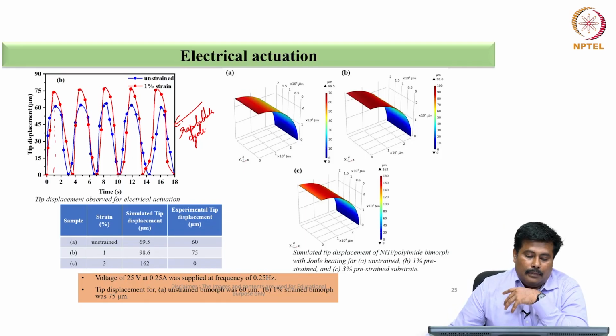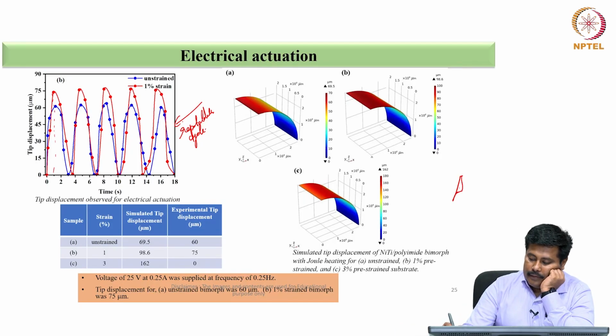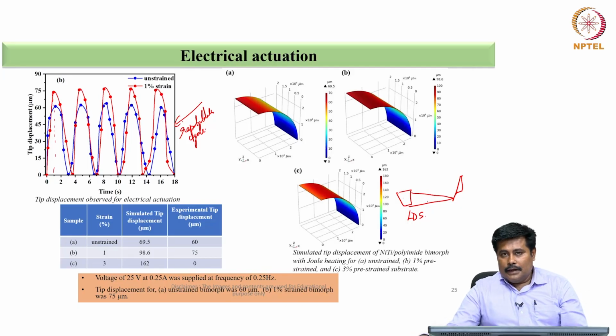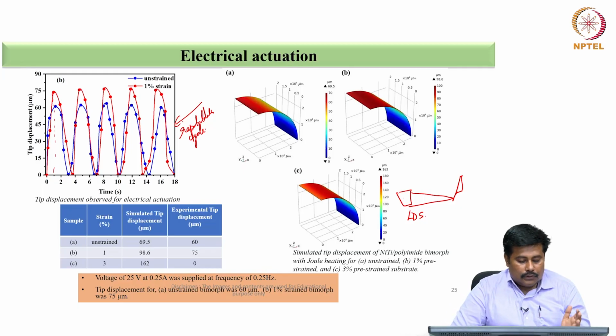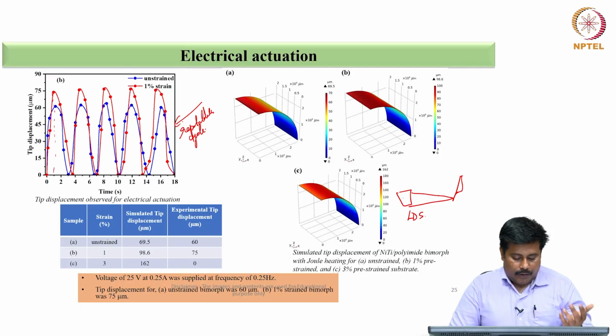In order to get this repeatability cycle, we keep the SMA bimorph, and then the overall repeatability of the structure can be monitored using a laser displacement sensor. In this laser displacement sensor, the light is made to interact on the tip, and when continuous actuation happens, there is a reflection, and from the reflection we can estimate the overall cycle. The voltage supplied is close to 25 volts, and 0.25 amps is the overall input to this system, and the frequency is close to 0.25 hertz.